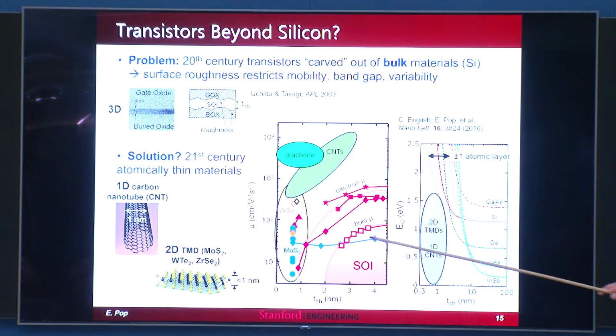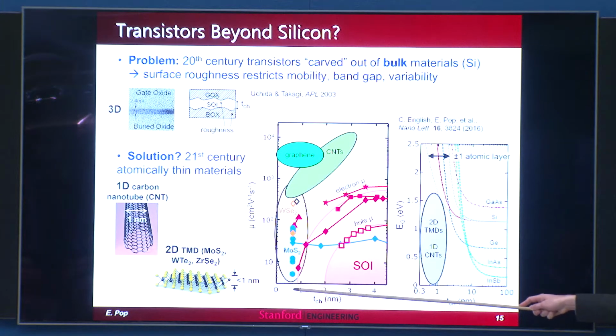So in fact, if you look at mobility as a function of thickness for these materials, this is experimental data that basically shows that below about 3 nanometers in thickness, whether it's a film or a fin, the mobility of silicon actually tanks. I mean, it goes from hundreds in doped inversion layers down to tens, down to very, very small values, and pretty much all entirely due to surface scattering and remote phonon scattering to some degree.